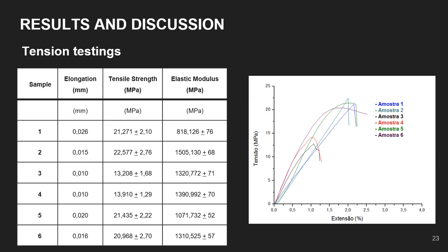From what can be seen from the results of the rupture stress test, the natural stiffness of lignin actually interferes with the elastic properties of the composites, since when comparing samples 3 and 1, the one with 5% lignin shows less deformation as well as lower breakdown stress. However, this deficiency with regard to the mechanical properties of lignin composites can be rectified with the joint use of the plasticizer PEG 400, since sample 5 demonstrated properties similar to the pure film.